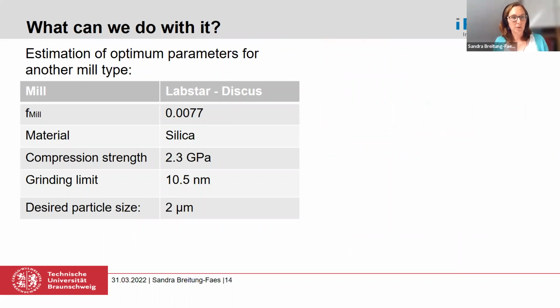As you have seen in the curves before, there were no results included for the disc geometry I showed you at the beginning. And now we had this industrial project where we got this disc geometry for our mill. And I said, okay, let's see what's happening if we grind material like silica. This was at least the thing the company would like to have. And so we calculated at least the F-mill factor from the geometry. As I said before, we had a silica. We know probably the parameters because silica was a material I used for my nanogrinding experiments as well.